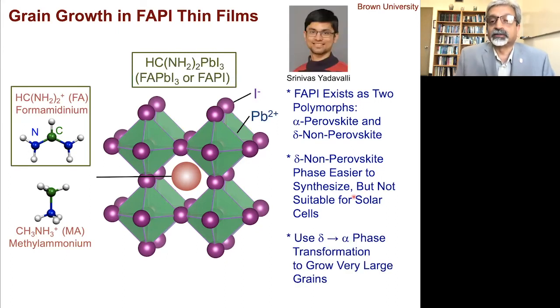But my student, Srinivas Yadavalli, PhD student, basically figured out a way to take advantage of that. So he can use this transformation from delta to alpha and basically grow these very large grains. So here is how it goes in a nutshell. This is a very fine grain thin film, about 0.2 microns grain size, and the thickness is 0.5 microns. So this is not very acceptable. And this is this delta phase.